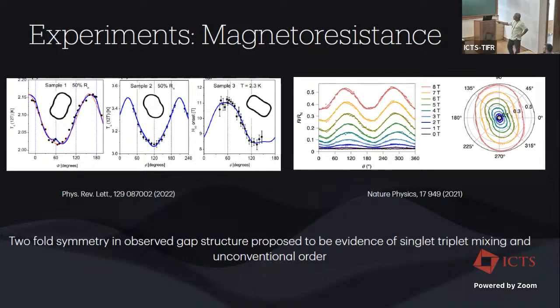What you find is that as a function of magnetic field, there is essentially this clear twofold structure that shows up, which indicates towards formation of a twofold symmetry in the superconducting gap. In zero magnetic field, the gap shows a hexagonal symmetry as we would expect from the lattice. But in a magnetic field which is in the plane, you have this twofold.